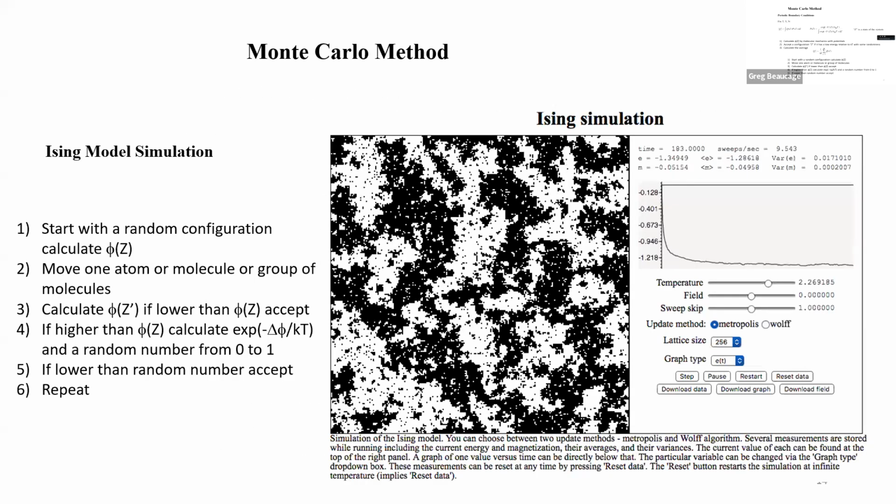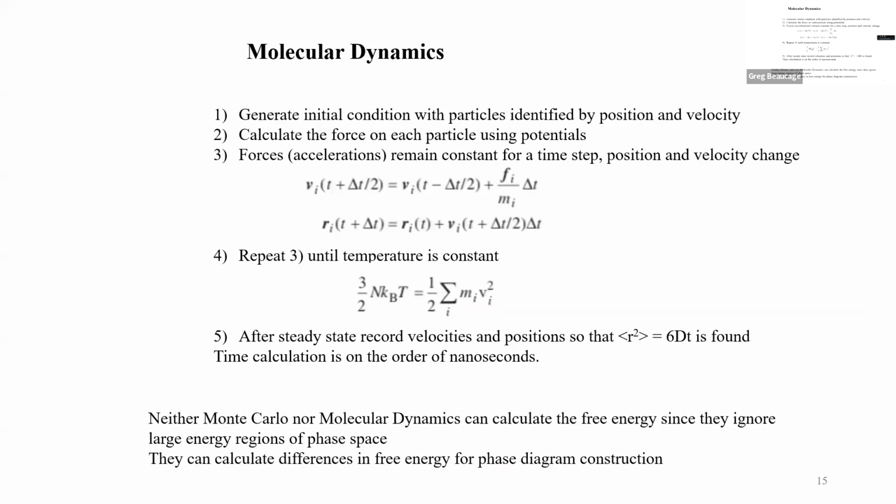That's supposed to just go through how you do the Monte Carlo. This goes through how you do the molecular dynamics, which is what the LAMMPS code is for, for the homework. Setting up an initial condition, you set up something and usually you do a warm up to get it to be in a reasonable state. The way you set it up, it could be that the atoms cross each other, right? So you throw that into LAMMPS and it'll have a setting for no crossing molecules, and you can let it run for a little while and it'll figure out what the positions are to not cross. So it hasn't reached equilibrium, but it's a place where you could start the simulation.